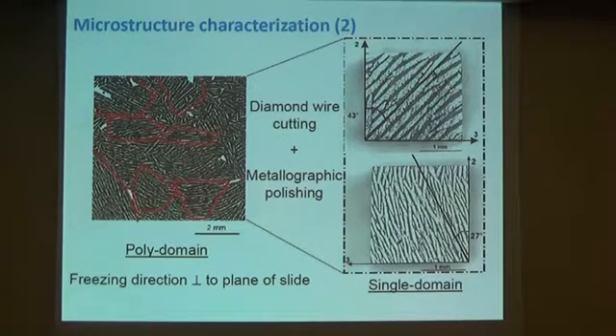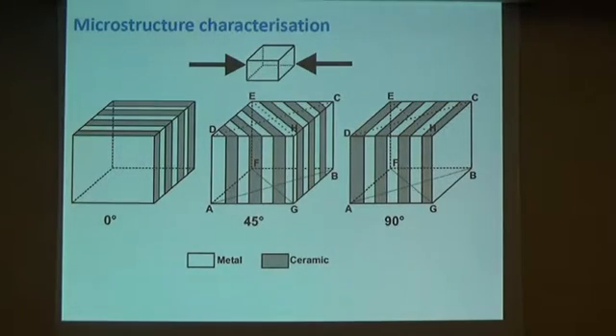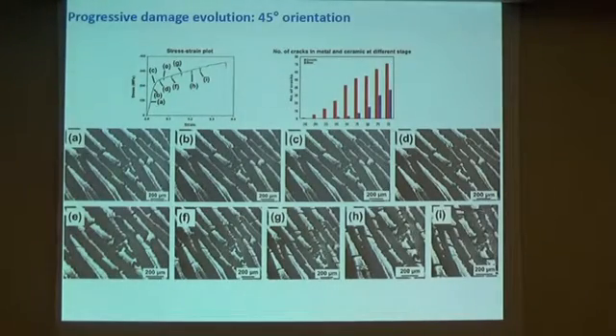So to investigate behavior of these composites, single domain samples were cut out of the composite and tested. You can see these single domains and samples cut out of them at different orientations relative to the freezing direction. And because the amount of material produced was quite small, samples were made for compressive testing, and they were compressed in a different direction relative to layer orientation. And this series of photographs shows you what happens to the layers when the material is loaded. So this is a stress strain curve, and each of the points highlighted with a letter has a corresponding photograph showing what's going on here.